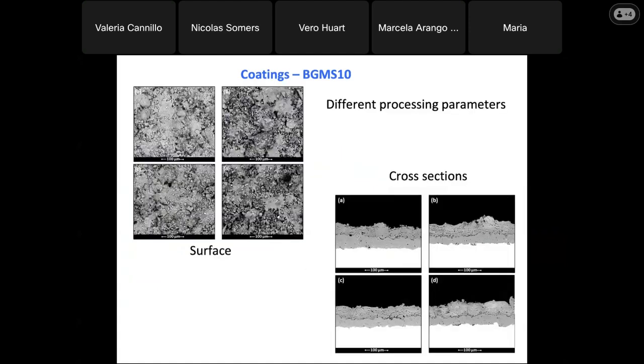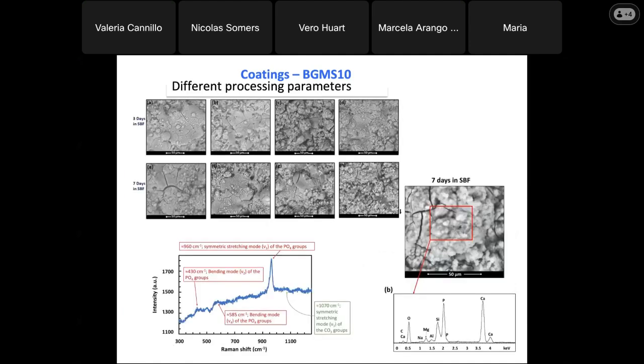So you can see the surface and cross-section of such coatings with different processing parameters. And so you can see that by varying some parameters of the torch, you can obtain different results. These coatings are particularly useful, for example, to coat a metallic prosthesis. And also in this case, we have results in vitro, for example in SBF and cellular results, which are encouraging, but we don't have in vivo results yet.